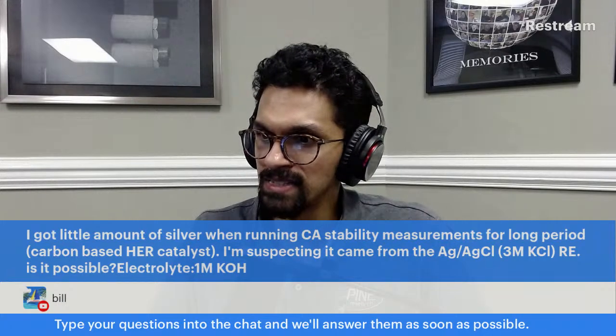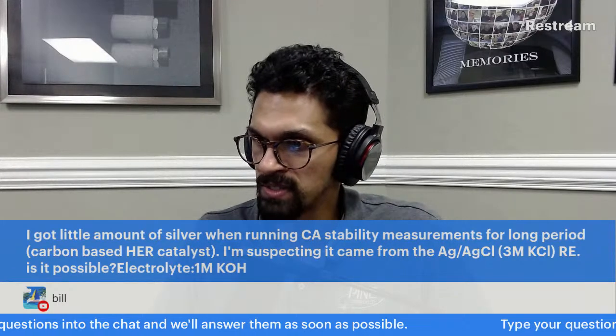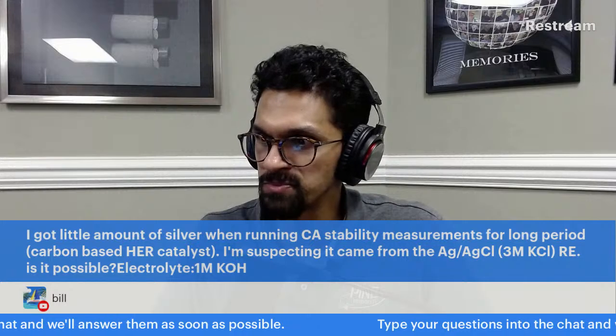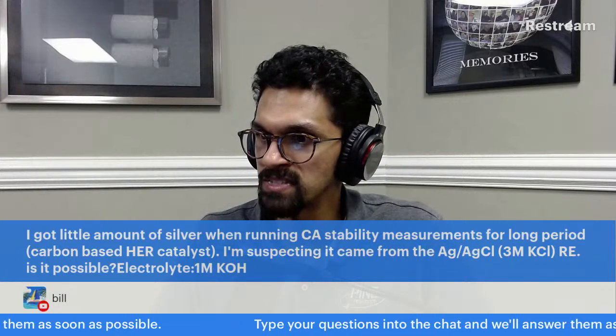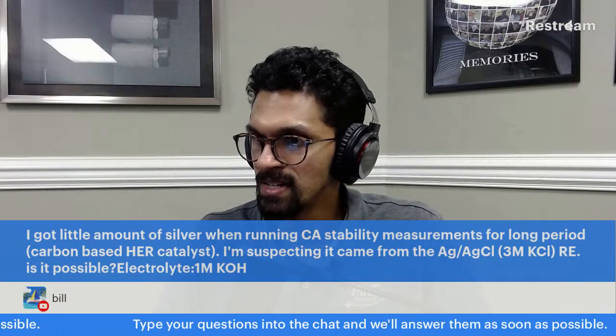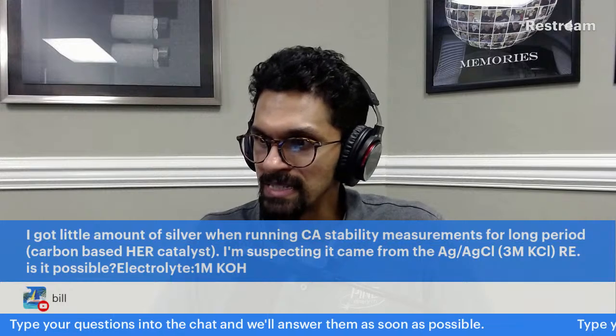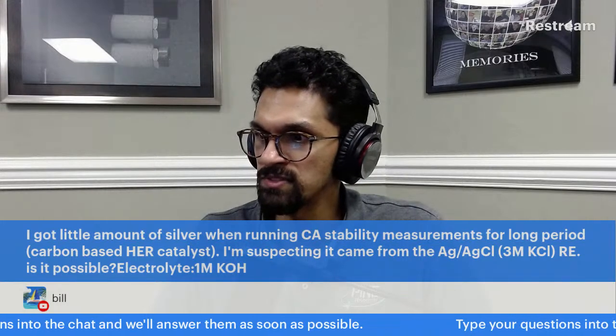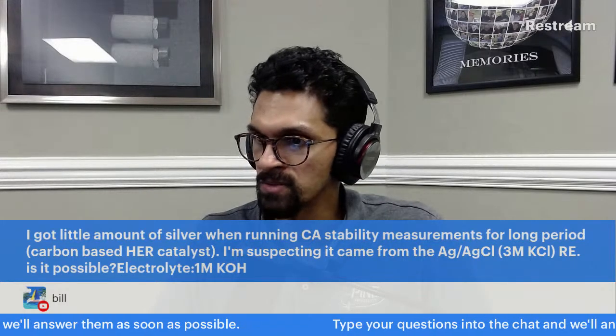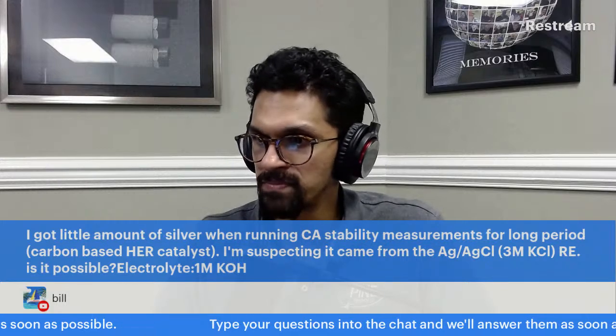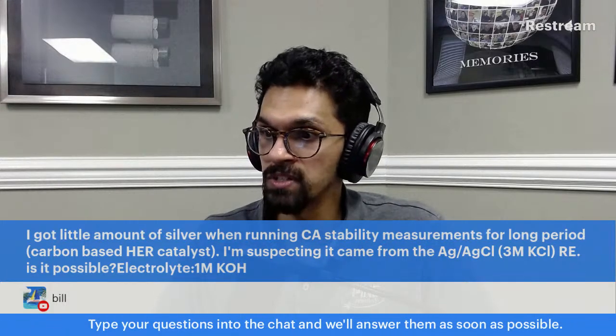Bill says, I got a little amount of silver when running CA stability measurements for a long period on a carbon-based HER catalyst. I'm suspecting it came from the silver chloride 3 molar KCl reference electrode. Is it possible? The electrolyte is 1 molar KOH.